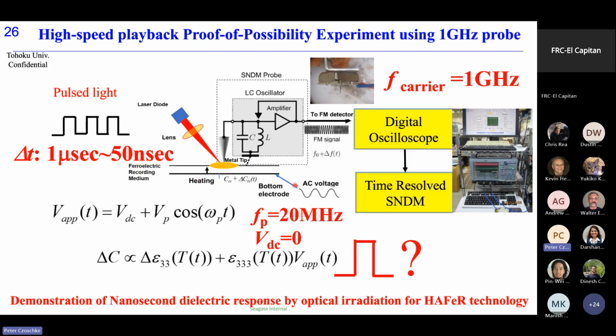Unfortunately, due to the restriction of the hardware, we could not apply a higher frequency of AC bias voltage. So we set the AC bias voltage at 20 megahertz. This means that the shorter part, less than 50 nanoseconds, is meaningless.